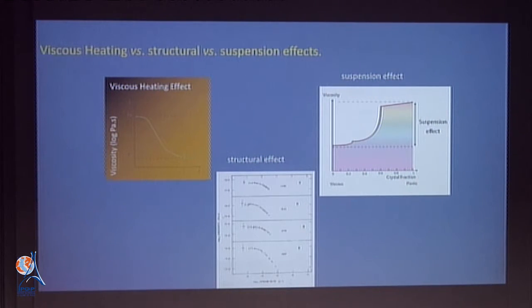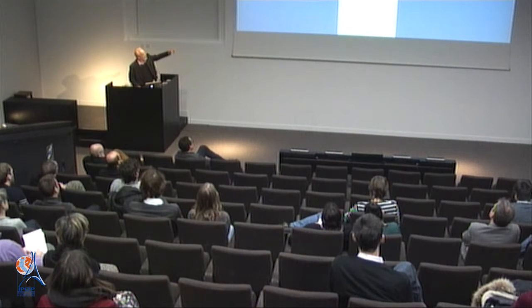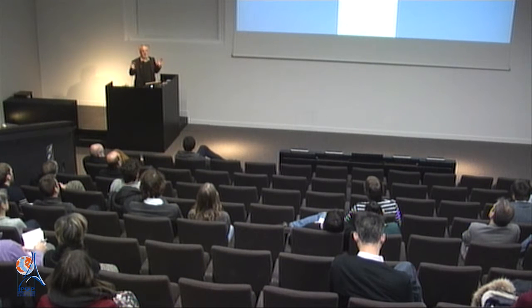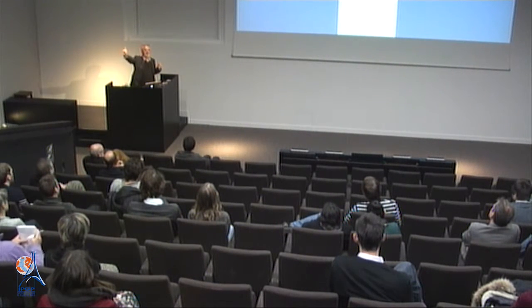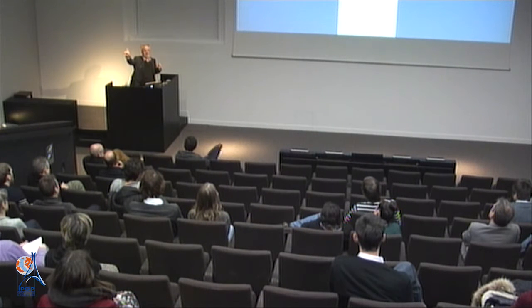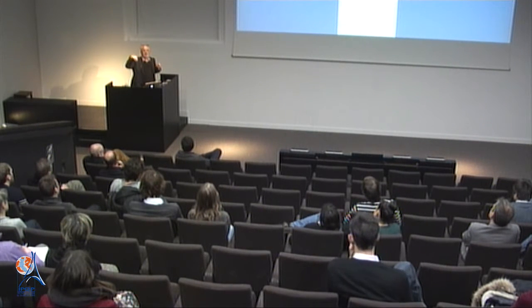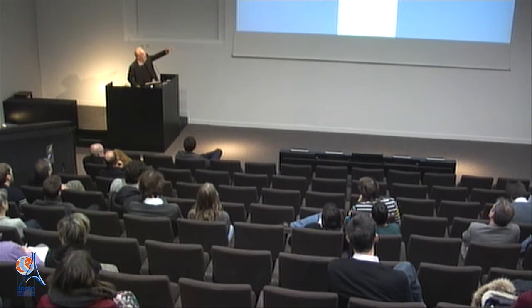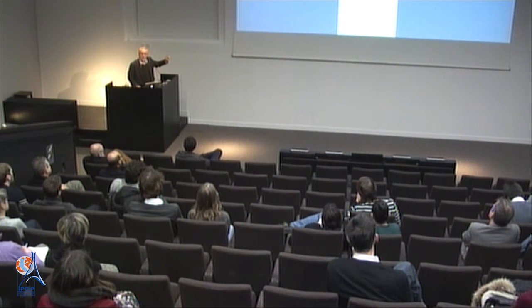We have the structural effect of the collapse of liquid structure that I show you in the middle there. So these things are going to shear thin, even if they're pure liquids. Even if a rhyolite is extruded with 95 or 97% glass, that material was still capable of shear thinning under the wrong or the right circumstances. And that's the effect in the middle.